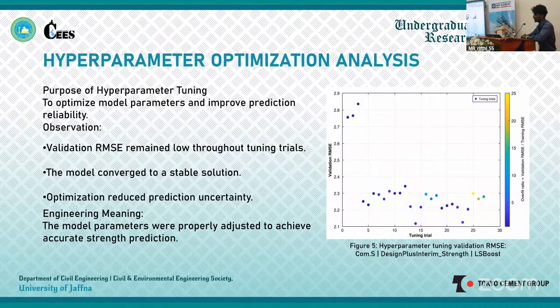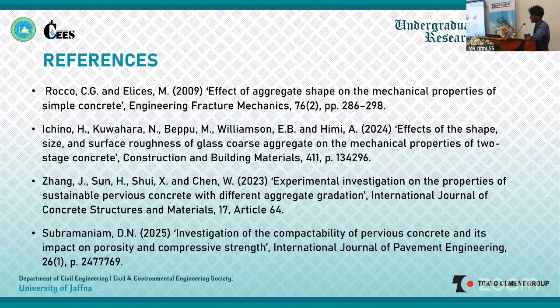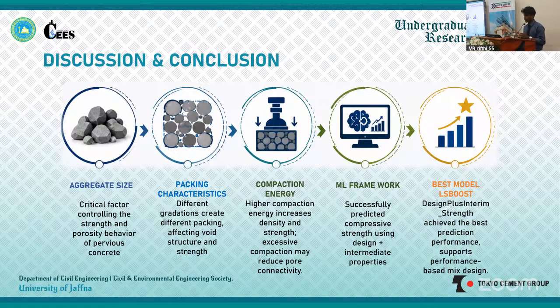And finally, the conclusion part. Aggregate size is an important factor affecting both porosity and compressive strength. Small aggregates increase the strength, while large aggregates increase the permeability. Higher compaction improves the strength, but too much compaction may reduce the pore connectivity. Finally, among all the machine learning models, the design plus interim strength configuration with the LSBoost model gave the best prediction performance. These are the references.